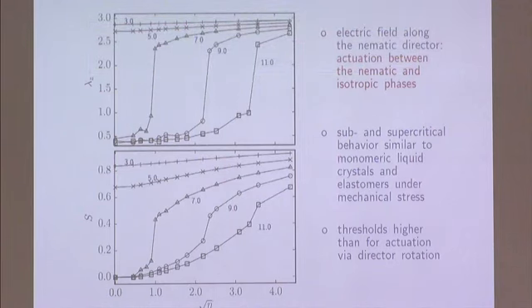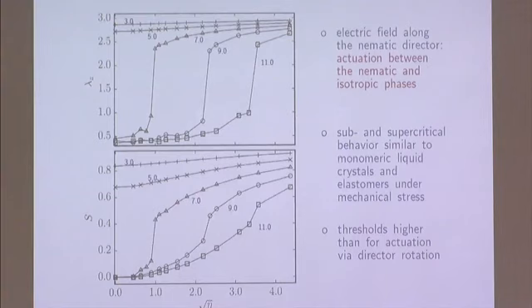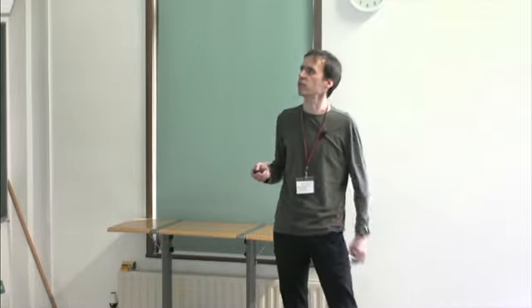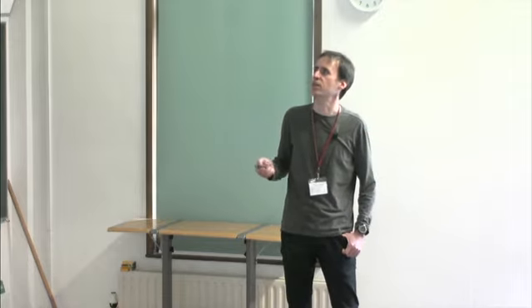So that was the more interesting part, applying a field perpendicular to the director. One can also, of course, apply it along the director and also see what happens with the isotropic phase. And like in this mechanical field case, we are able to induce a transition from the isotropic to the nematic phase, but in this case, it turns out that the thresholds are much higher than the ones estimated for the so-called semi-soft rotation, semi-soft actuation, and they don't seem to be so promising.